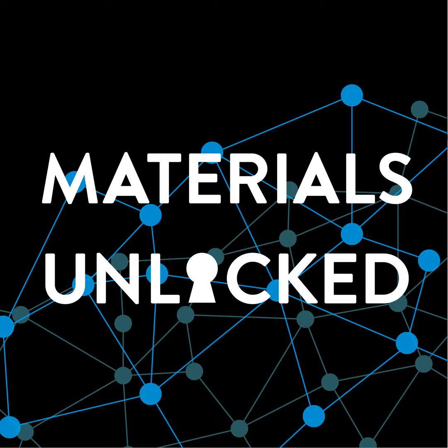And just simple things like that. So just give us an idea, how quickly is this going through the mill? Oh, yeah. This is the thing that, when people come and observe, is always the most underwhelming part of it, because it's done so quickly. We'll say, well, we'll need about 4 to 6 hours to do that, so by the time we heat it up and we're waiting, and then you put it through the rolls, done. So, Lincoln, you've missed it.